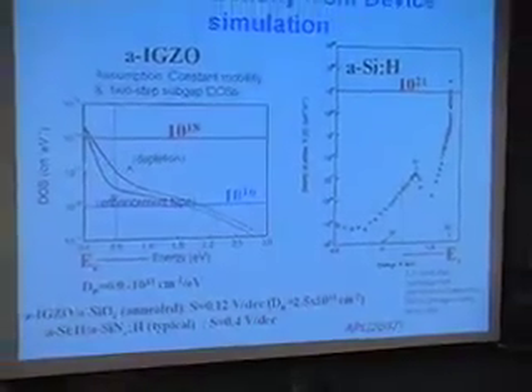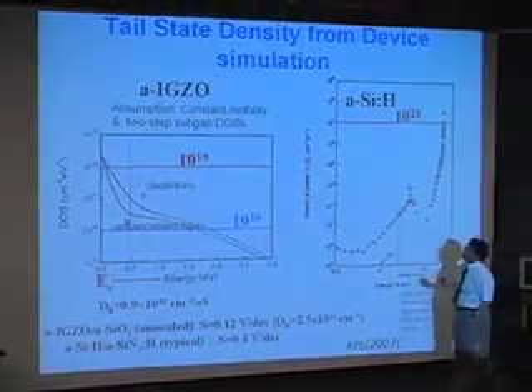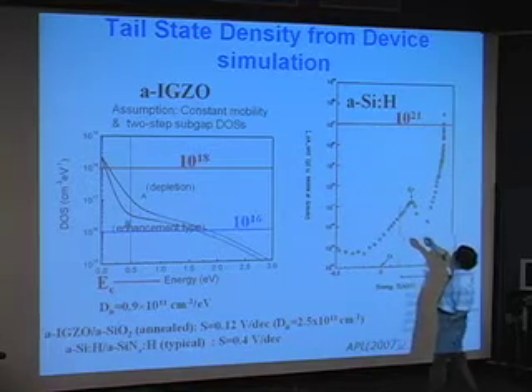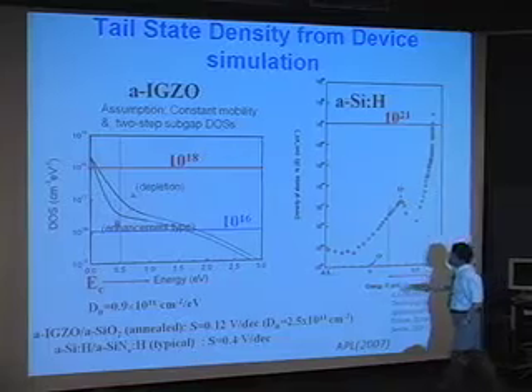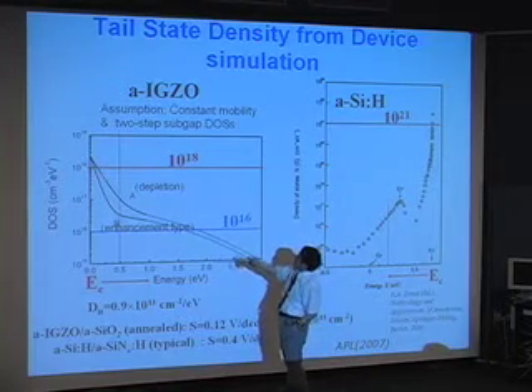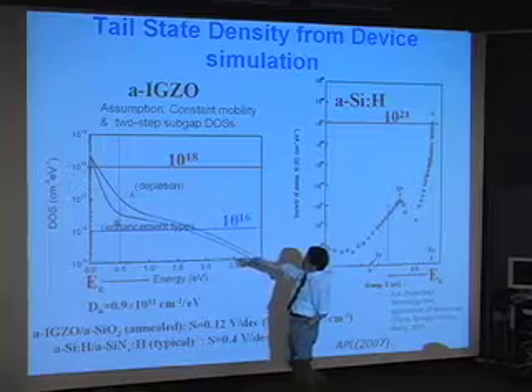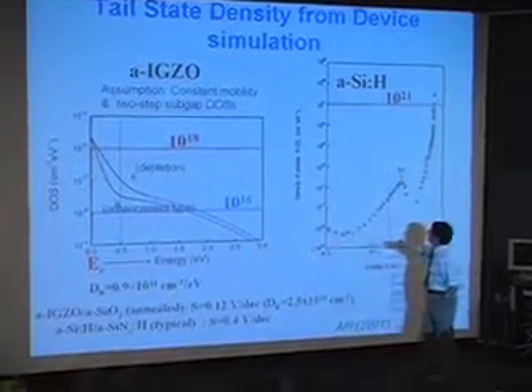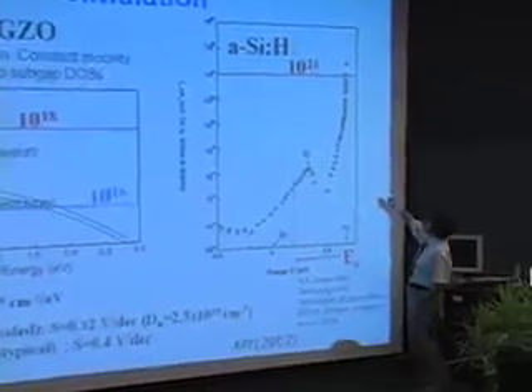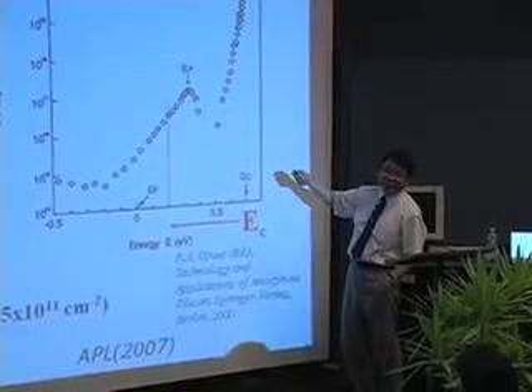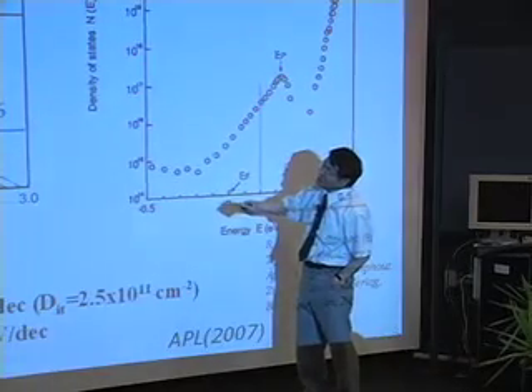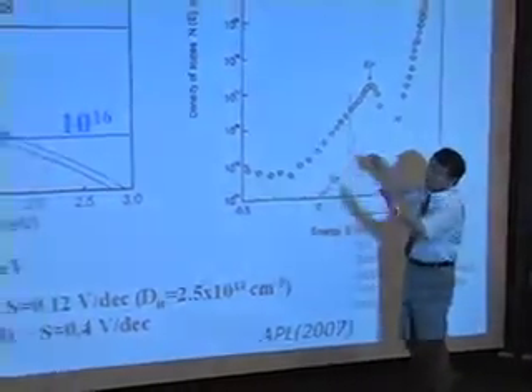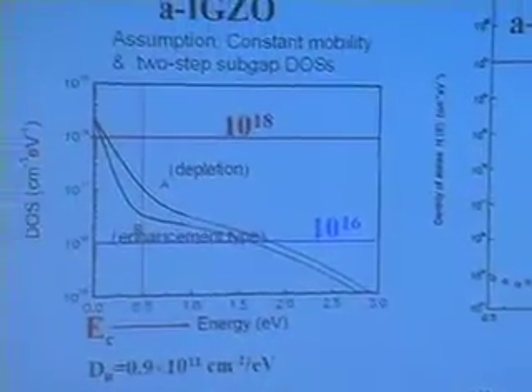I will show the defect state in amorphous oxide semiconductor in comparison with amorphous hydrogenated silicon. The defect state in amorphous oxide semiconductor is 10 to the 18th. This is the data for amorphous hydrogenated silicon, 10 to the 21st—three orders of magnitude different. That's why when a carrier is doped, the Fermi level can easily exceed such a defect level. This is totally different from amorphous hydrogenated silicon.